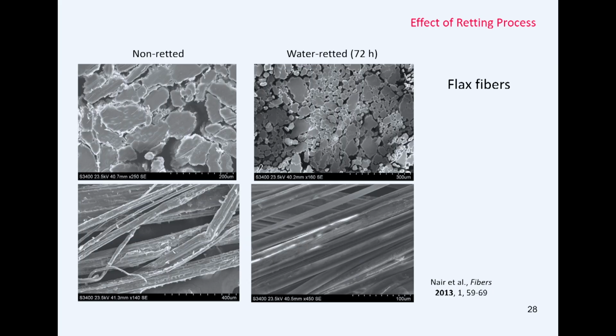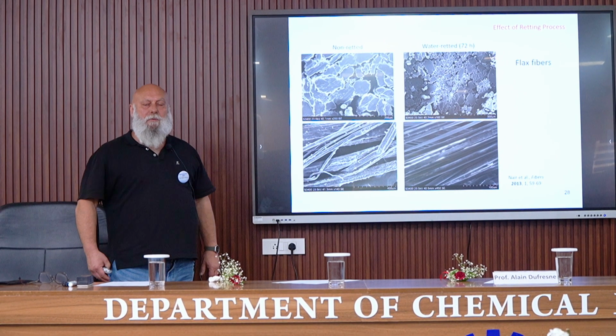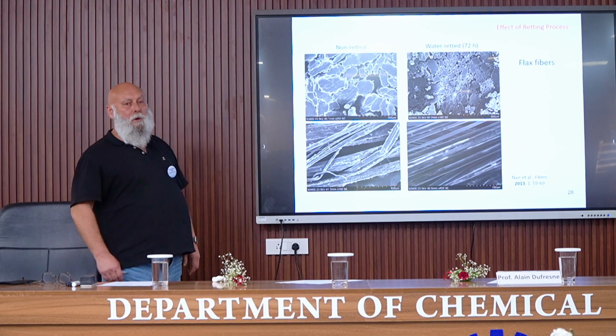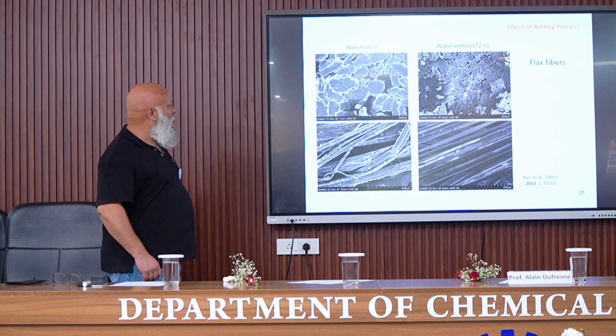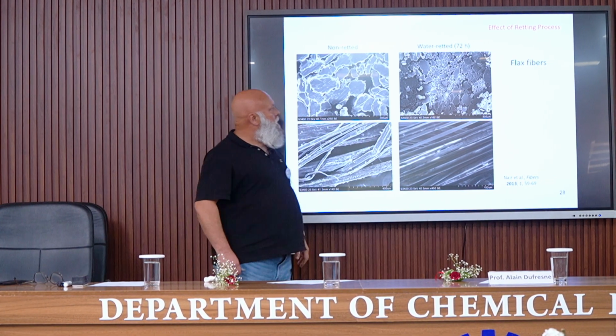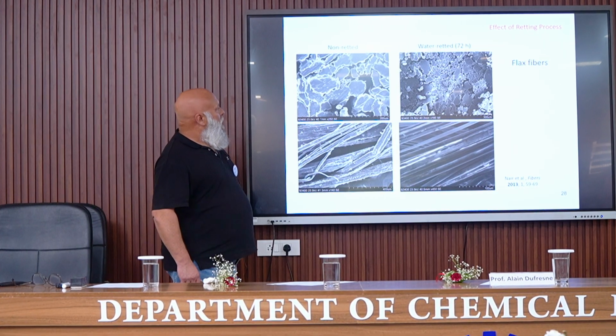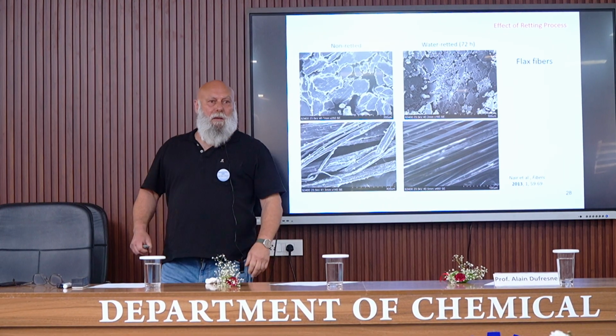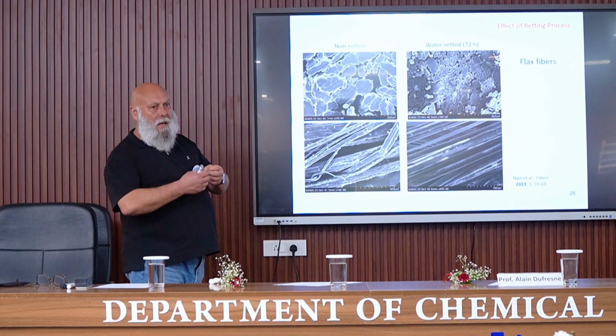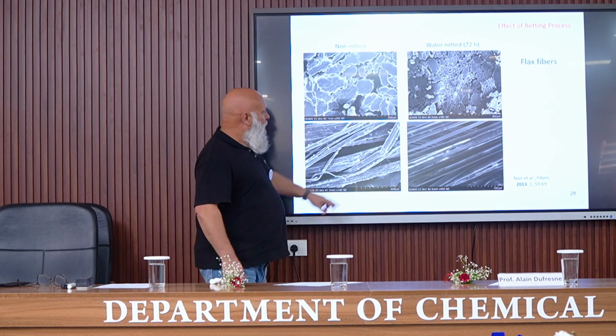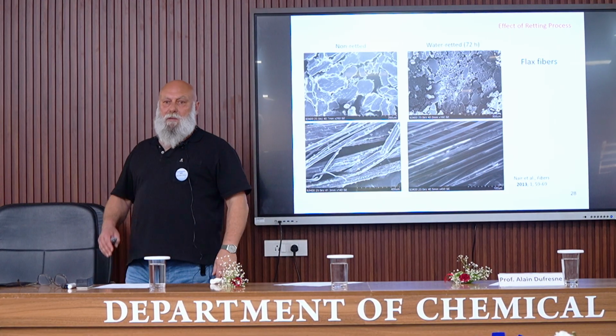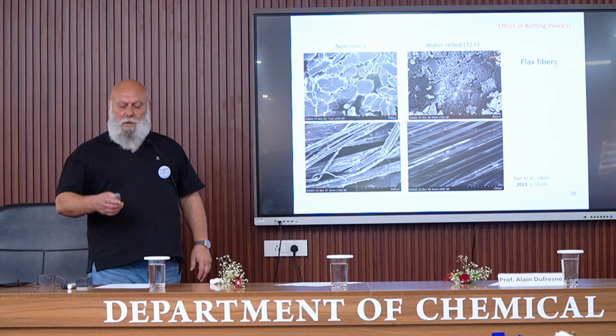This is for flax fibers, so you have to remember, yes, it's a different orientation of the fiber. So for non-retted fibers, you can see that we have some agglomerates or bundles of fibers, and you can see also on the surface of the fibers some roughness. This roughness comes from the presence of non-cellulosic material like lignin and hemicellulose. And after retting, in this case water retting for 72 hours, we can see that we have separated more or less the fibers, not individually, but at least the bundles are not so big. And you can see that the surface of the fibers is smoother because of the removal of non-cellulosic materials.